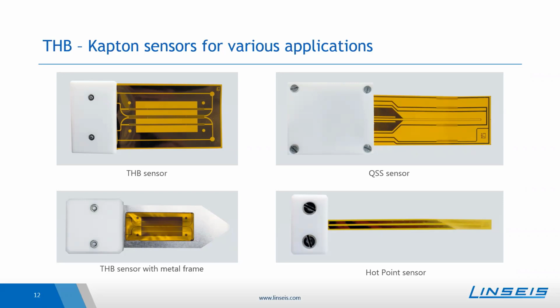The same requirements also apply to the single-sided sensor. So a minimum thickness of 3 millimeter for lower conductive samples should be offered, and for the higher conductive samples, maybe 10 millimeter. In general, the sample should cover more or less the complete sensor surface. So the complete sensor foil, the sensors have a size of 20 × 40 up to 40 × 80 millimeter. The QSS sensor is about 25 × 55 millimeter. So for the THB, rather large samples are needed. Regarding the maximum sample size, one is more or less completely open. There are just some minimum requirements for the sample sizes for the THB measurements.